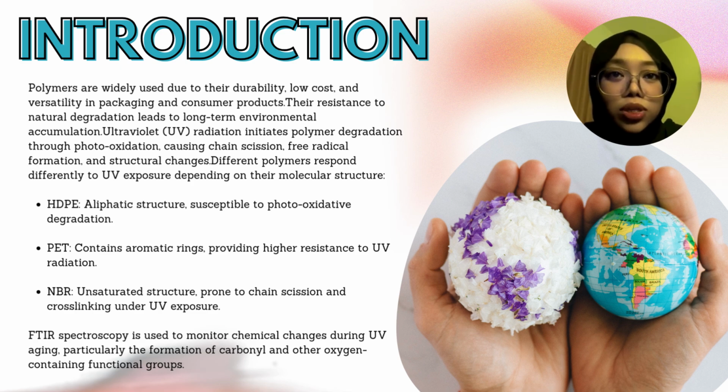UV exposure can trigger photooxidative reactions that break polymer chains, produce free radicals, and cause chemical and structural changes. Over time, these processes may lead to fragmentation of plastics into smaller particles. Different polymers respond differently to UV radiation depending on their molecular structure.